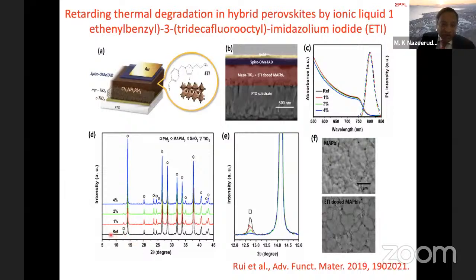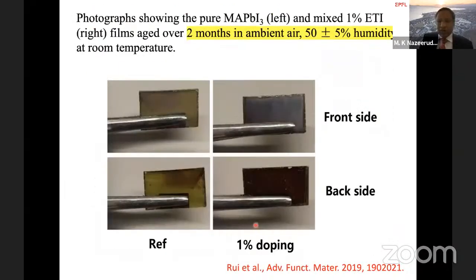Now, without going into the detailed configuration of these solar cells, if we use this ionic liquid, look at the reference sample: it produces lead iodide, showing the decomposition pattern. However, if you have 1%, the decomposition decreases significantly. If you have 2%, it further decreases, and at 4%, there is no formation of lead iodide, showing the stability of these materials. Here is the blown up data. This clearly shows that no formation of lead iodide means the material is quite stable.